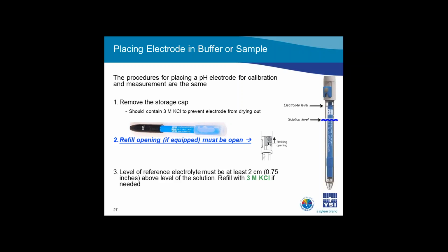Next, if using a refillable electrode, make sure the fill hole is open for both calibration and measurement. This is very important and a commonly missed step, especially if using a refillable electrode for the first time. Next, if using a refillable electrode, make sure the level of the reference electrolyte is higher than the level of the buffer or sample. The reference electrolyte should be at least 2 centimeters above the level of the solution that you're measuring or calibrating in. If it isn't, refill the electrode with 3 molar KCl or the electrolyte used by your sensor.